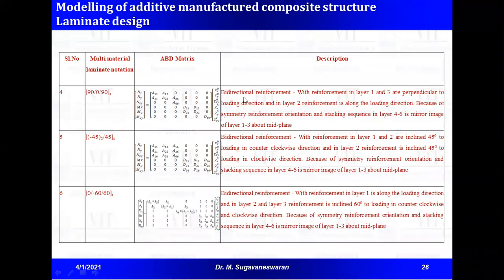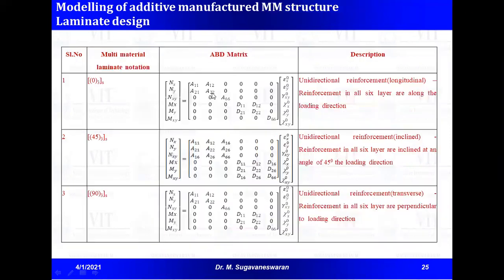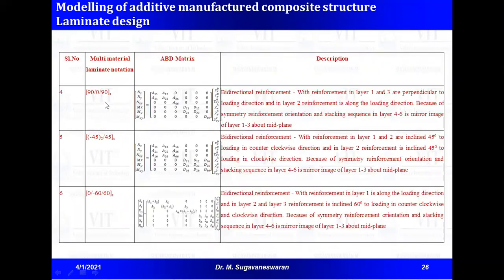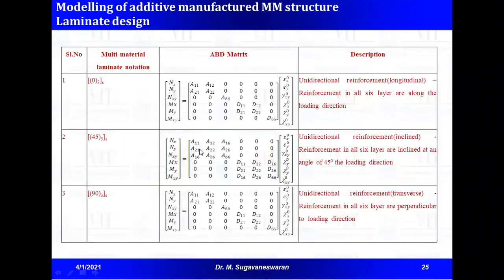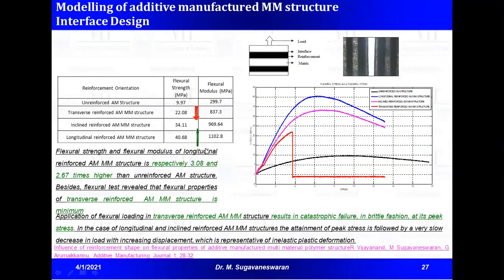That is bidirectional, that is, from one layer to another layer you will have a variable orientation. In the previous case, in all layers we have the same orientation of secondary material, whereas in the bidirectional, with each layer we are able to change the direction. Again, the relationship is displayed in this CLT equation. The last one is quasi-isotropic, where we are able to achieve a transversely isotropic condition. Now, the CLT guidelines will help us to design the secondary material from a primary material through a CAD model.